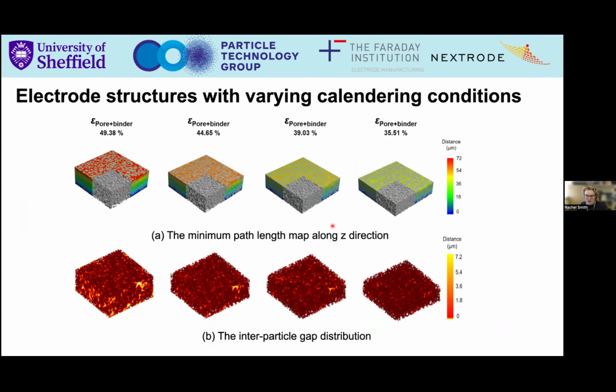So what we can do here is we've effectively made all these different structures with different porosities, and we can look at, okay, what is the minimum path length in different directions? And that minimum path length is really important for understanding our lithium ion transport. So how is it going to be able to transport around these particles? As I said, as we compact the electrode, typically our lithium ion transport becomes more difficult. And we can also look at interparticle gap size distribution.